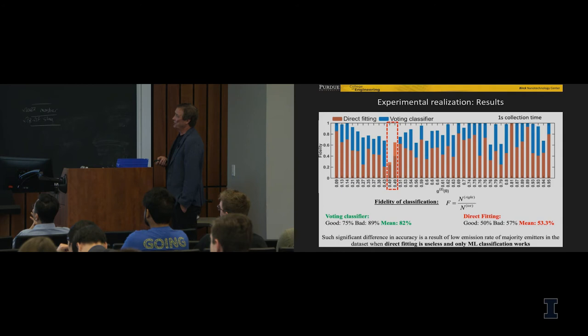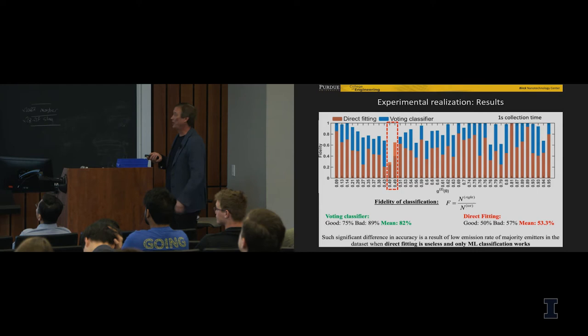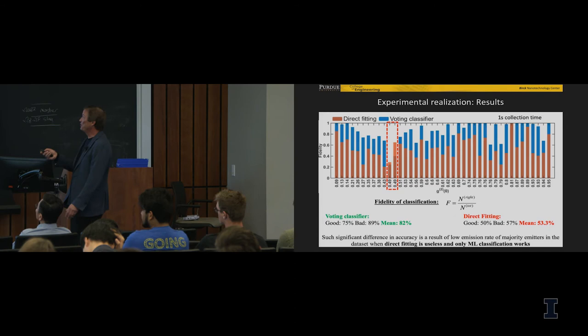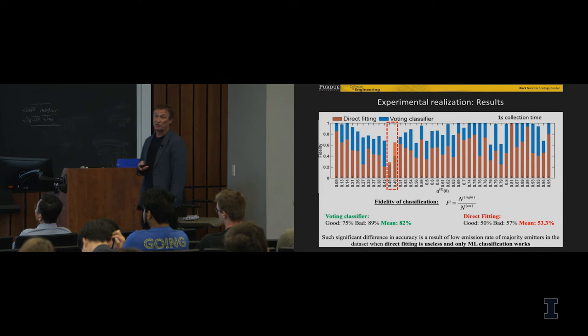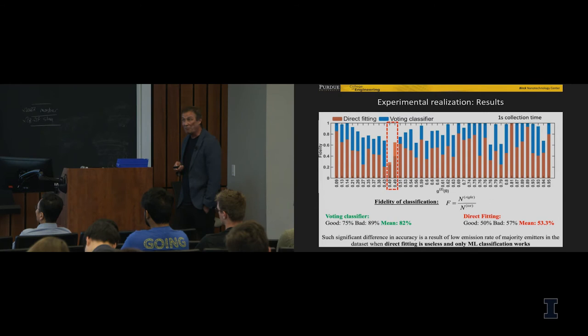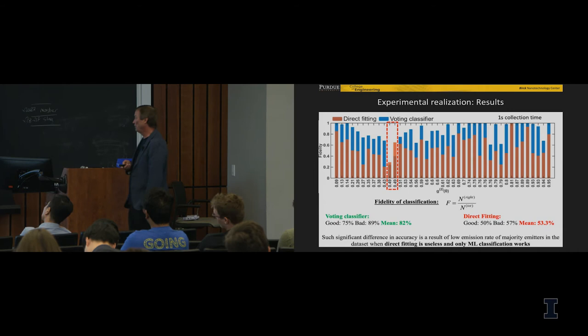So if you do this collection time like 1 second, a very sparse set of data, with the conventional way, by using this direct fitting, the fidelity of your prediction, fidelity being the number of events where you correctly predicted whether it's single photon or non-emitter to the total number of events, is basically around 50%, meaning that it's a random guess. Of course, it's either single photon or not single photon. So it simply means it doesn't work at all. Whereas with this machine learning approach, with a fidelity close to 80%, you actually could say whether it's a single photon source or not. That's a clear difference. And as I said, for rapid prototyping, when you have to deal with many elements on your quantum photonic circuitry, there is no way to do it other than using machine learning as far as you could see.